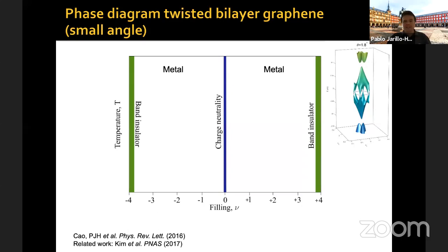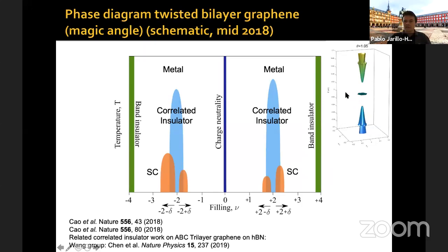Now, what happens for magic angle graphene? Okay, these bands become very flat. And now if you zoom in and you put carriers in your flat bands, as you put 1, 2, 3, 4 electrons or holes per moiré unit cell, we have, in addition to charge neutrality and band insulators, these correlated insulator states that happen around 2 and -2 electrons or holes per moiré unit cell. Yeah. And then as you dope, at -2-delta, -2+delta, etc., you have superconducting states, okay? Now this was the situation in mid 2018.